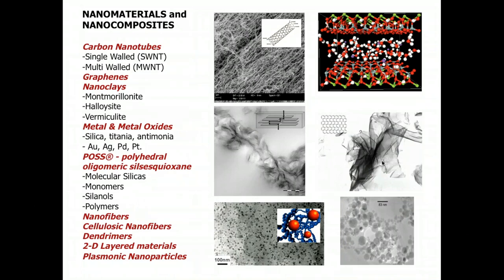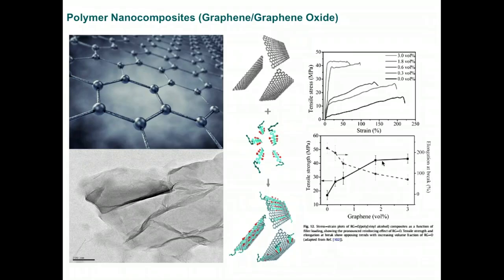I will show you the approach we took with polyurethane and nanocomposites. Just with graphene, when incorporated in plastics such as PMMA or polystyrene and properly nanostructured, it can improve the thermomechanical properties of polymers by extending their modulus, elongation at break, and so on. This has been very well known for a long time with bulk materials processed by molding or extrusion methods.